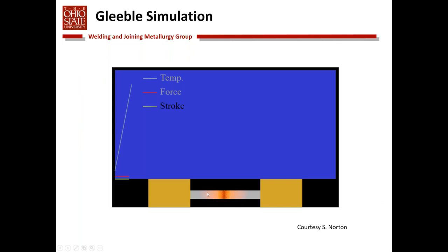So this is our heat affected zone thermal cycle portion of the test. As we cool that down within a certain temperature range, we're going to apply a strain. And so at the end of the test, the sample is cooled to room temperature, but we built a substantial force or residual stress in the material.